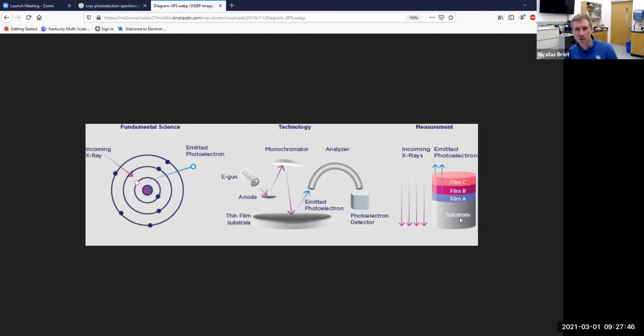Because, for example, what we've been doing so far in EDS, when we do a spot at the surface, even if you see silver, if the silver is only in the first couple hundred nanometers, you are really underestimating how much silver there is, because a lot of your signal is coming from what's below, which might not have any silver. So when the EDS is telling you a composition, it's telling you an average composition of the whole volume that's been probed, which might artificially decrease the silver content because it's very thin. Now, XPS is going to be so close to the surface that it's going to be able to really show you what's at the top of the surface.